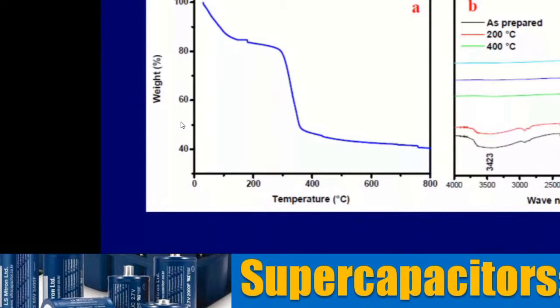The first stage, going up to 100 degrees, we say is the evaporation of water on the surface, and the interior also has some amount of water that exits around 200 degrees. The entire conversion of nickel hydroxide to nickel oxide happens around 350 degrees, and that is indicated by a large change, say from about 82 to 50%. And this is something that you want to understand.